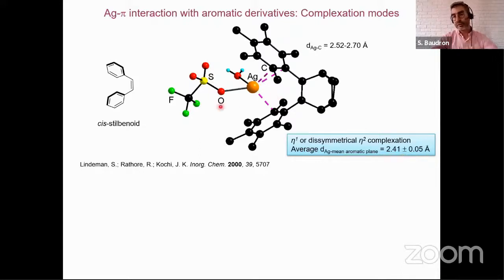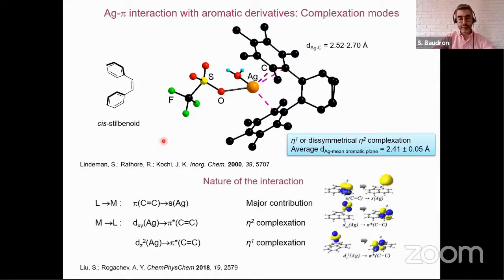If you would consider a classical model, you would expect the silver to sit on top of a carbon-carbon double bond in an eta-2 mode. And as you can see here, this is not experimentally what is observed. This has been recently rationalized by the group of Liu and Rogachev in this paper, where they showed that there were different contributions, as expected for this interaction. The main one is the ligand-to-metal contribution, as shown here.